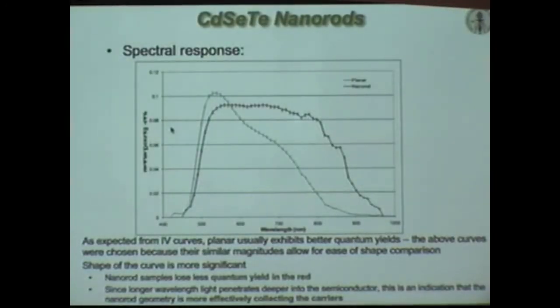Here's the data. You can see, in fact, that the planar structure works as advertised and reported previously in the literature. The band gap is about 800 nanometers. You only get a fraction of the photons absorbed, collected as yield, and that fraction increases up to all of them only when you get to very short wavelengths, but you lost almost all the solar spectrum photoactivity in the meantime.